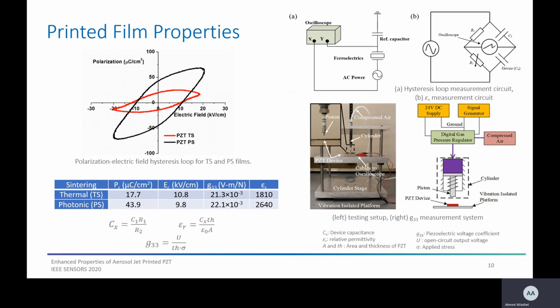The polarization-electric field hysteresis loop is a key tool to study the ferroelectric properties of the PZT material. The ferroelectric properties obtained are summarized in the table, and you see in the ferroelectric loop the black curve for the thermally sintered and the red for the photonically sintered. We can see a clear distinction in the performance. High remnant polarization was obtained in the photonically sintered film, reflecting better ferroelectric properties than the thermally sintered group. Superior piezoelectric voltage coefficient and relative permittivity values were observed in the photonically sintered films. This indicates that photonically sintered PZT would have a better piezoelectric response and higher charge storage capacity.